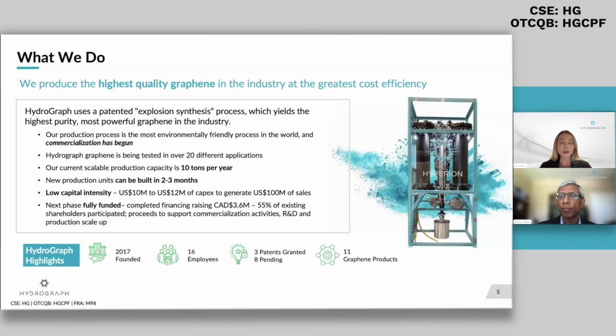What makes HydroGraph unique is that we own the patents for our proprietary explosion synthesis process, which yields the highest purity, most powerful graphene in the industry. If you look to your right, you can see a real image of our unit. This is roughly 2 meters by 2 meters. We pump in acetylene and oxygen. We ignite this with a spark from an electrode, and we are able to yield high purity graphene.